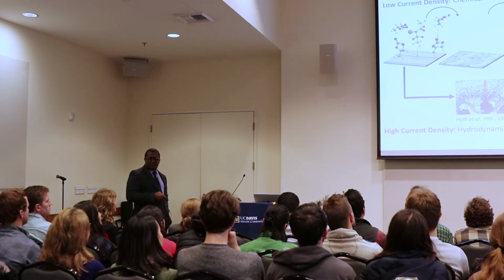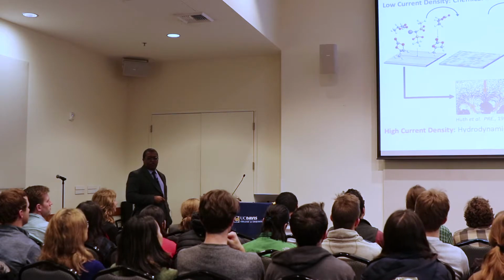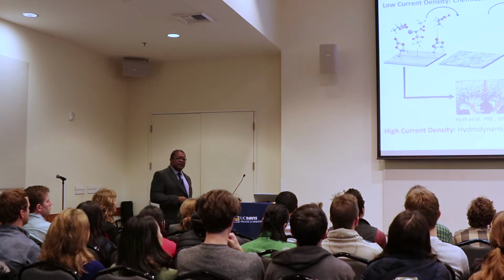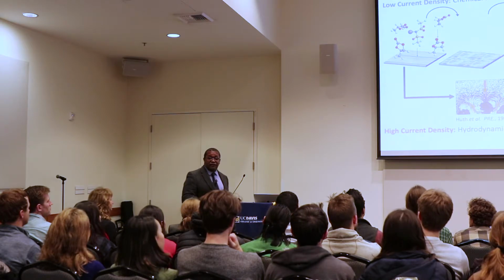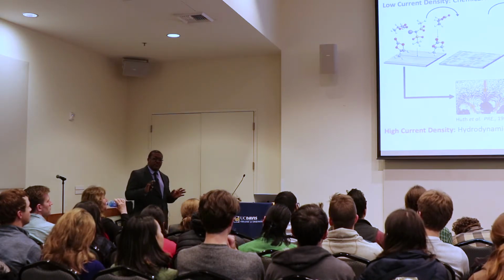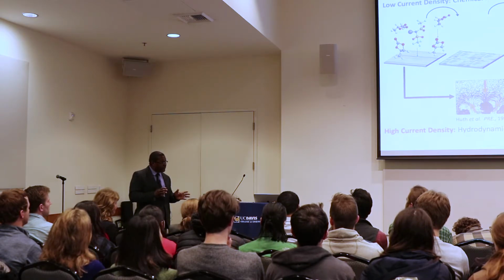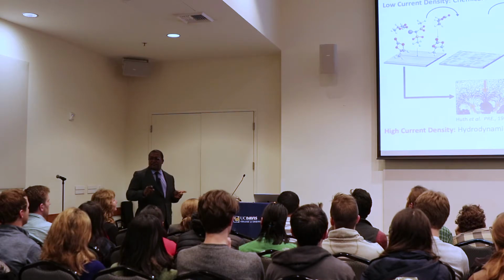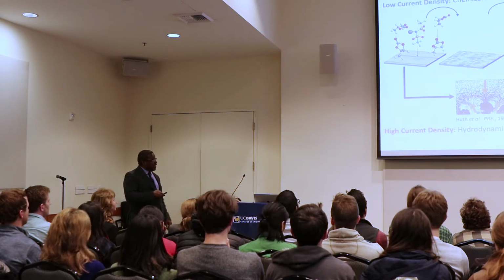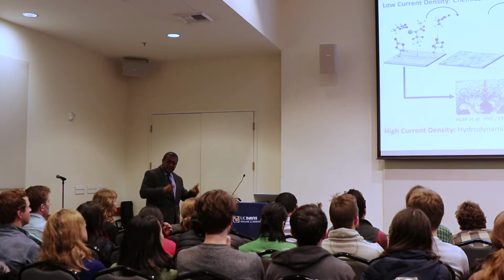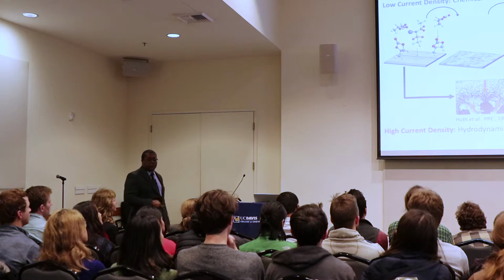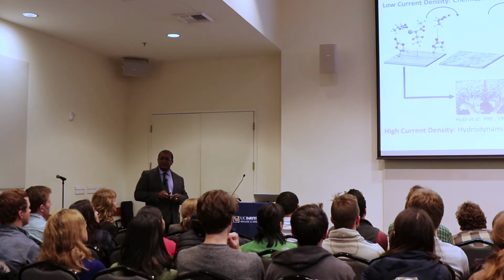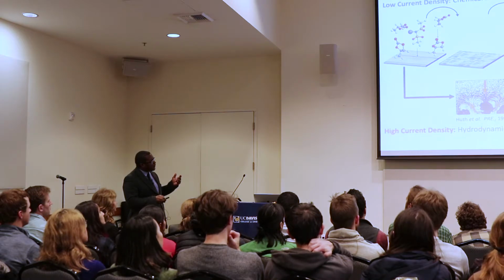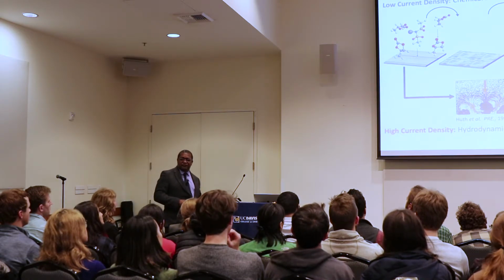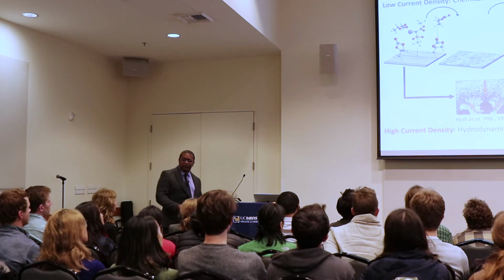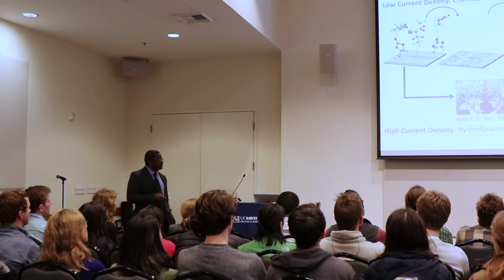Now, if you thought, well, why not just go to high current densities? It turns out you get hit by another problem. That other problem is actually an electrochemical instability called electroconvection, where in a battery where you would think there should be no flow, no convection because it's a closed system, everything is stagnant, suddenly flow fields start to be generated at high current densities. And these flow fields have a certain pattern. They have this kind of roll cell pattern where they dump material preferentially at certain spots on the electrode. So the end result is that here by chemistry you get bumps, here by hydrodynamics you get bumps, and the rest is the same. The bumps concentrate the field lines, and the end result is the runaway instability.